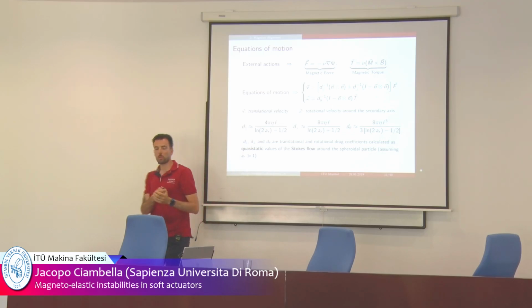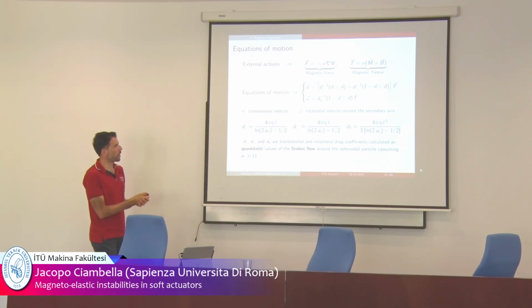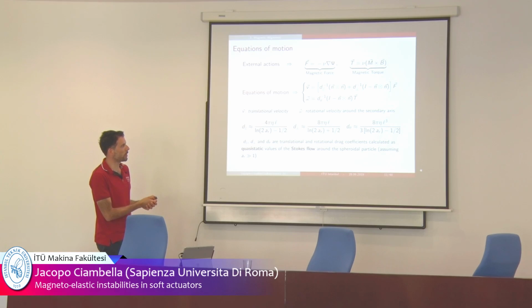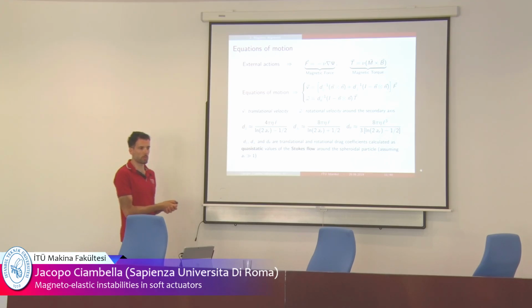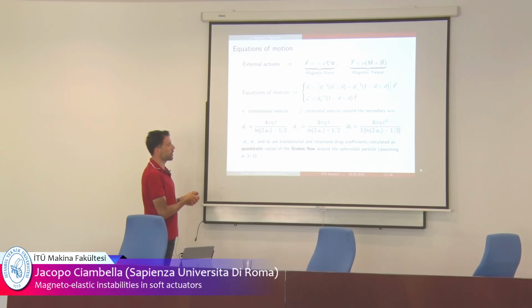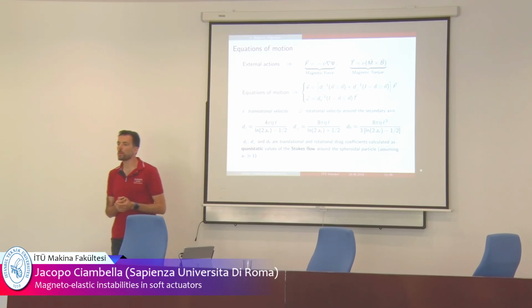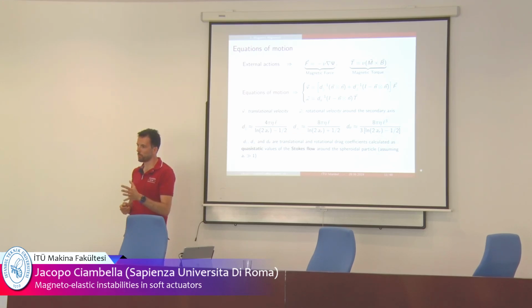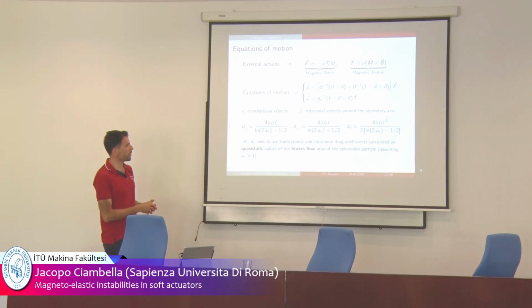So in the equation of motion, you have these coefficients, d parallel, d orthogonal, and d theta, which are nothing other than the drag coefficients. Because remember, this particle is embedded in a viscous fluid. And because of the ellipsoidal shape, as I said before, these drag coefficients are known in closed form, or at least in approximate form. So L, in fact, is the length of the particle, AR is the aspect ratio, and eta here is the viscosity of the solution.